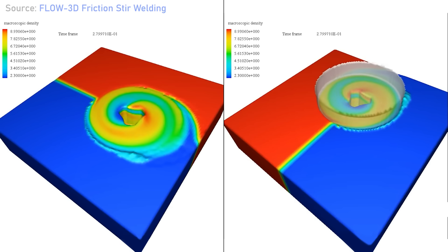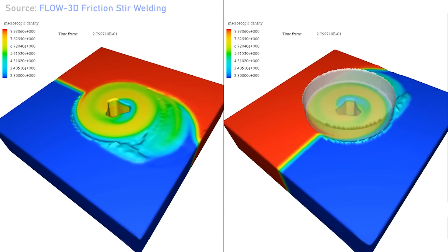Another advancement is aluminum-lithium and the ability to friction stir weld it. This is a remarkable technology — invented decades ago but has become very practical over just the last couple of decades. Instead of using heat to weld two pieces of metal together, it literally stirs the two pieces. There's a pin that rotates at a certain rate, placed between the two plates, moved at a very precise speed. It heats the material only a little from friction — you can immediately touch the material after welding and it's just barely warm.